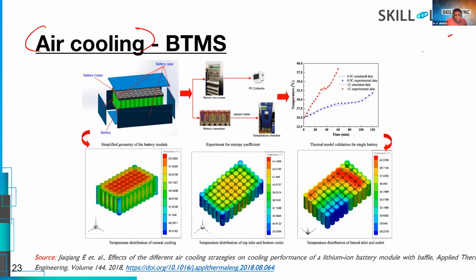This is the temperature distribution of natural cooling, done by a CFD tool like ANSYS Fluent. Here you can see the natural convection of heat from the battery to the surroundings, where there are hot points at the center. At the outer circumference of the battery pack system, the heat is less, since those batteries are in contact with the surrounding air, where there is convection heat transfer. So the outer batteries have lower temperature compared to the center battery. At the center we have 52 degrees Celsius, while the outer case has 47, so the delta T is almost 5 degrees Celsius. This is without a cooling process.